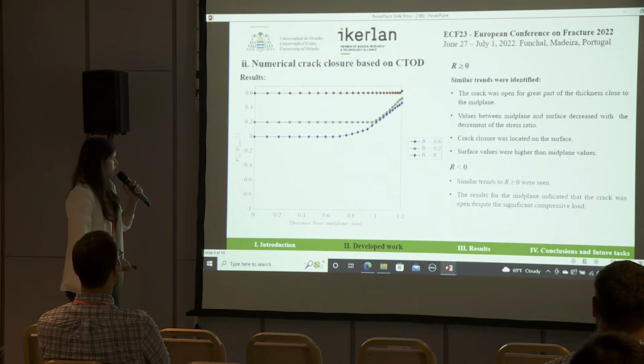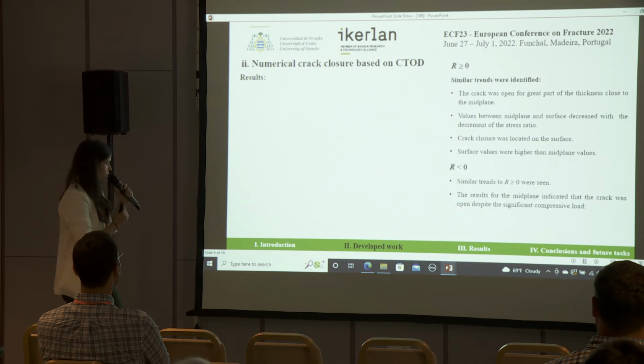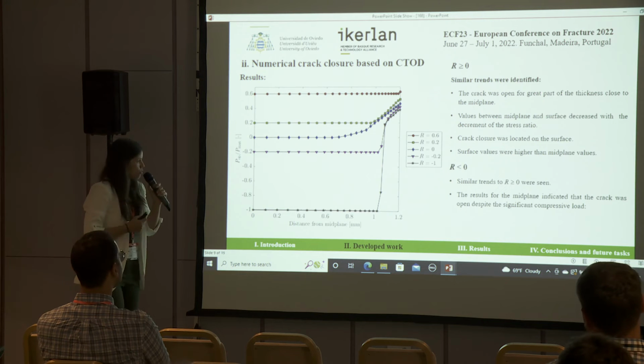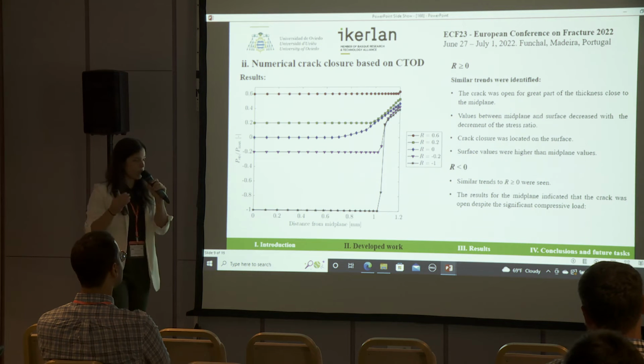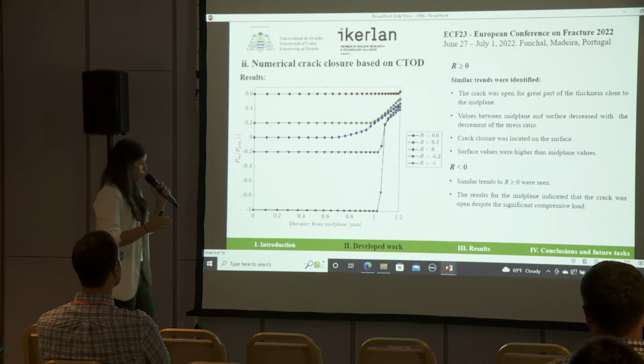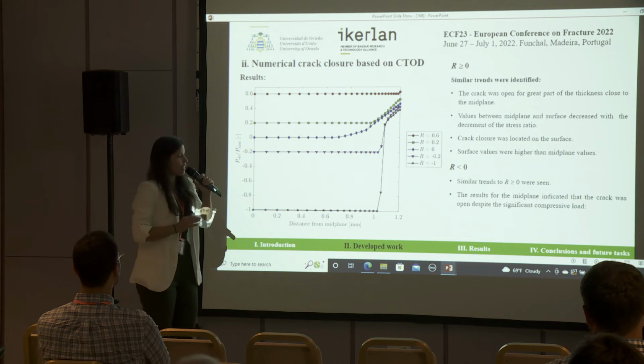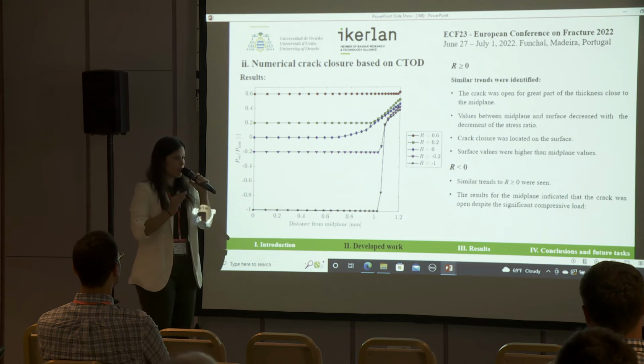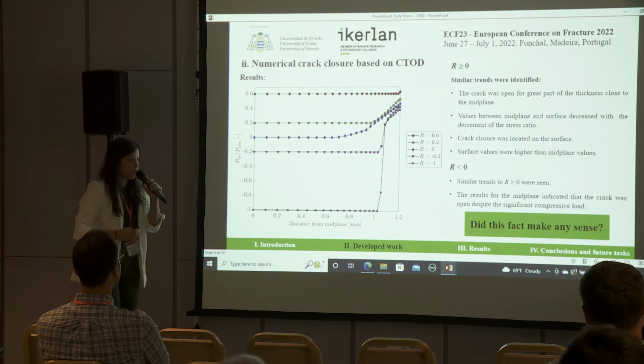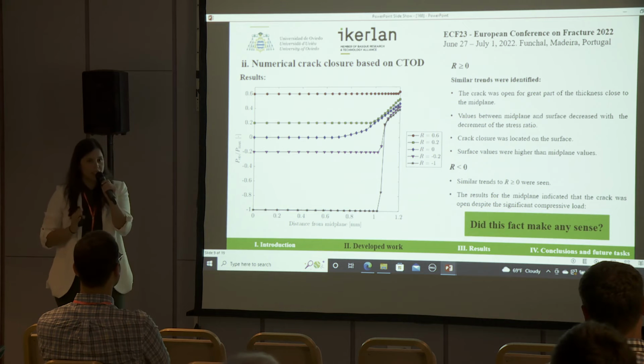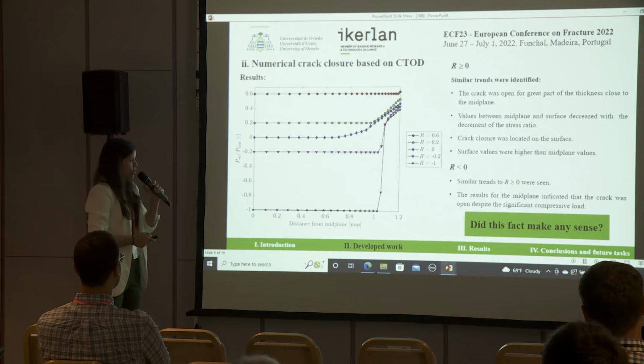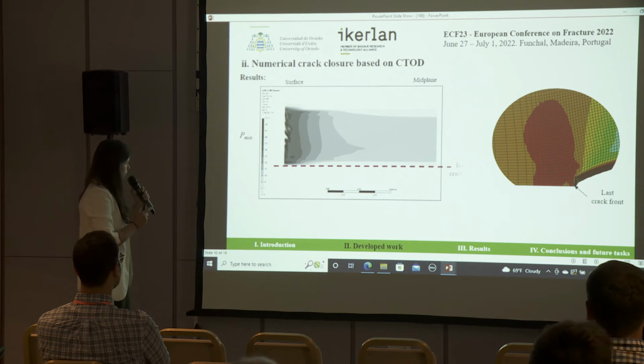On the other hand, focusing on the negative stress ratios, similar trends to those obtained for positive stress ratios were identified. However, the results for the midplane indicate that the crack was open despite the significant compressive load here. So the question was, did this fact make any sense? Let's try to answer it.